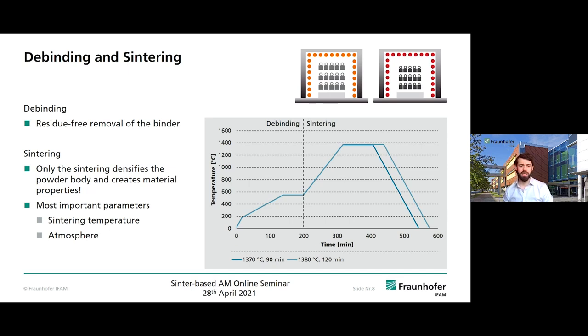And afterwards comes the sintering. Sintering is the process that defines the material properties. All the steps before were the shaping process, and the sintering creates the properties out of the powder body. And the most important parameters in sintering are the sintering atmosphere as well as the temperature.